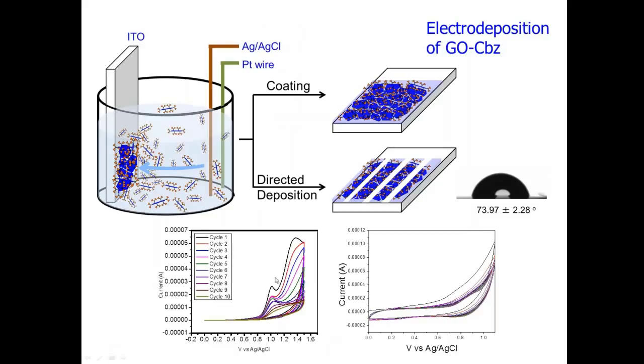Nevertheless, the cyclic voltammetry method allows us to track the deposition of these platelets on the surface of the ITO to form this complex or patterned layer.